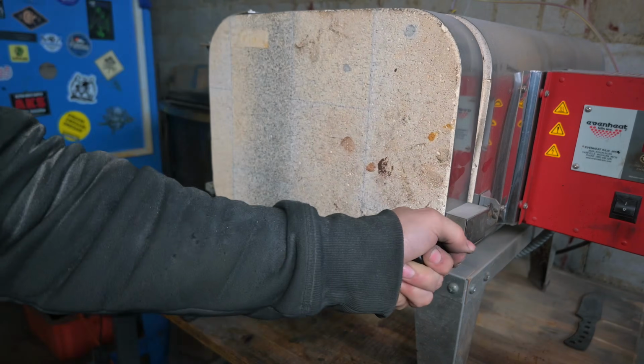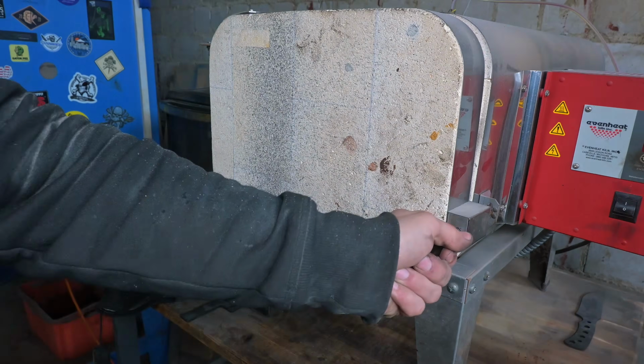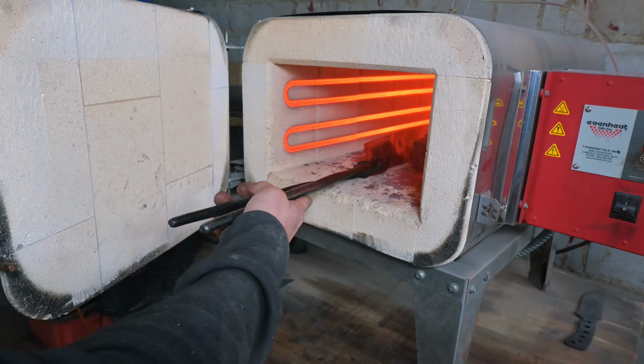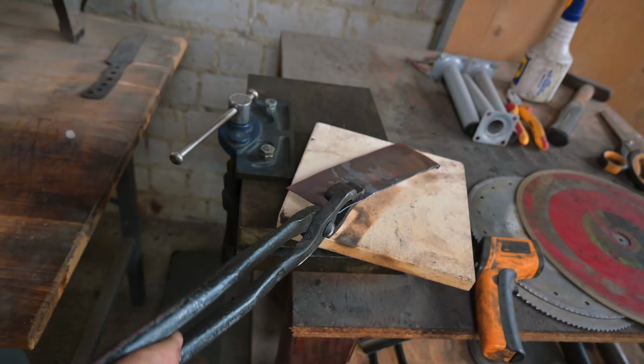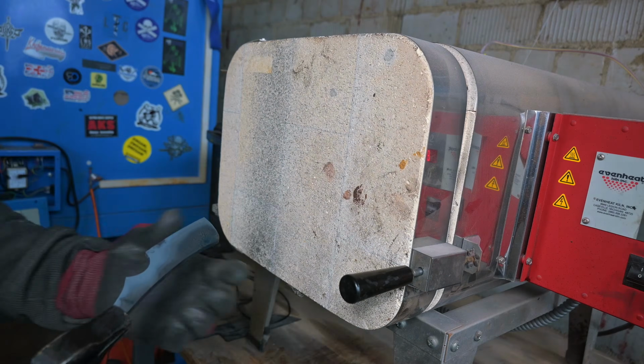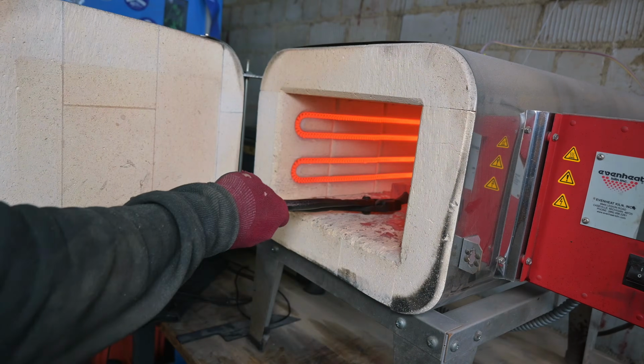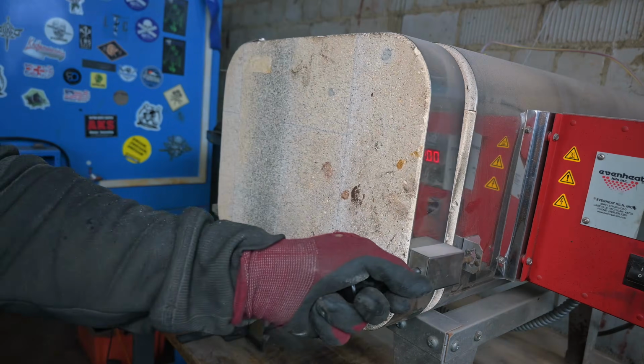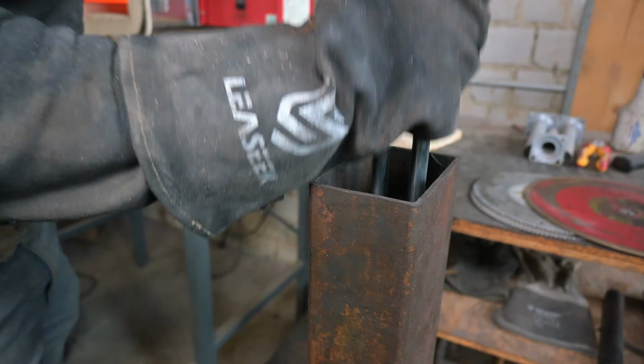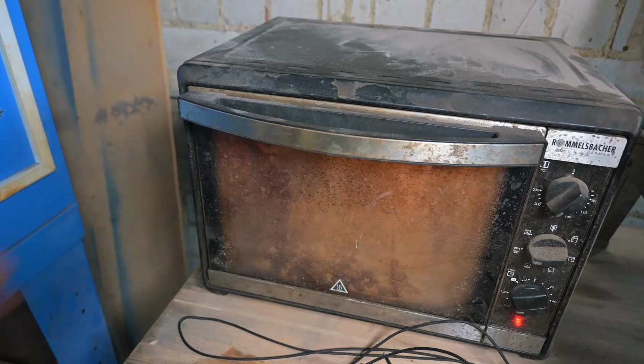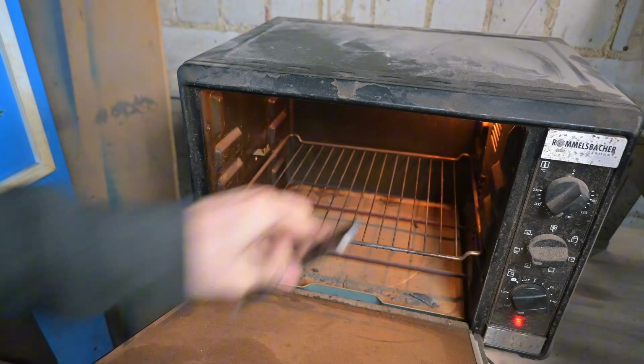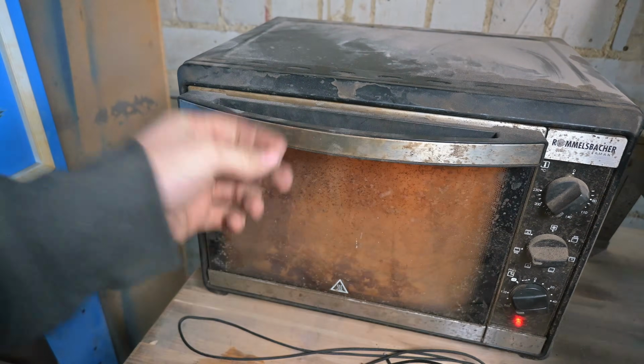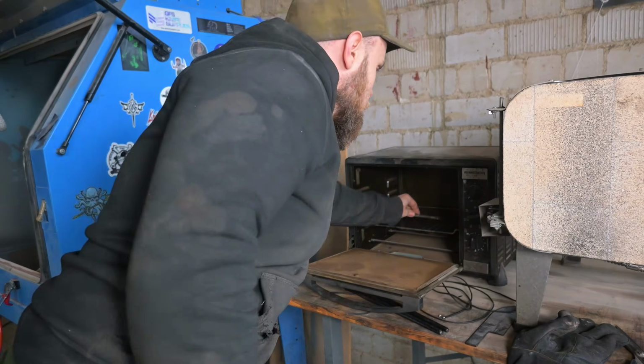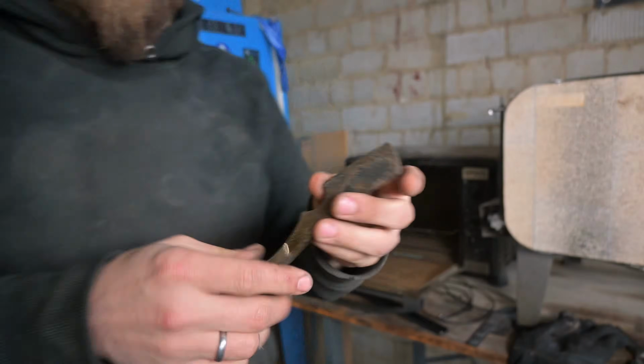Now to the heat treatment. Before I hardened the razor, I made three normalizing cycles to relieve the steel from any kind of stresses I put into it while forging. I then proceeded to quench the knife in my quenching oil, and after the quench was successful, I went right into the temper. So, still a little bit hot, but it's now time to grind it.